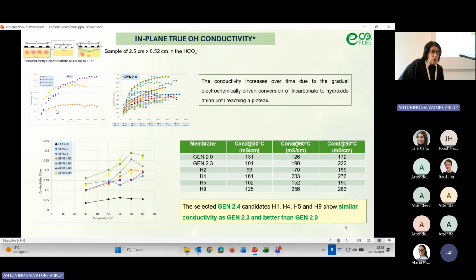The benchmark is the orange one that has the lower conductivity with respect to the Hydrolyte membrane. Here there are all the 18 membranes, but in this case, this graph is the conditioning of the membrane, and when the line reaches a plateau, it means that all the groups are converted. So after this, we started with the measurement of the anion conductivity, increasing the temperature.